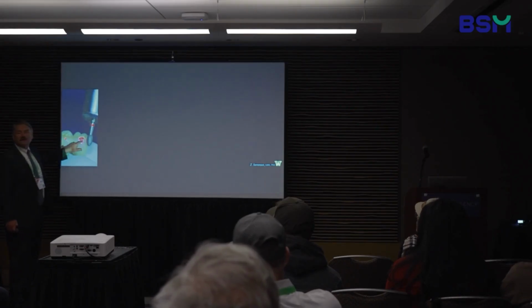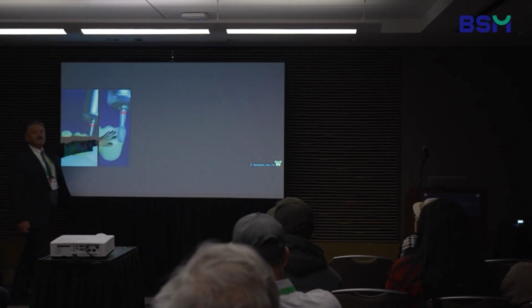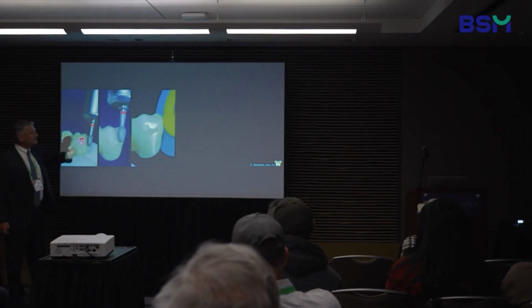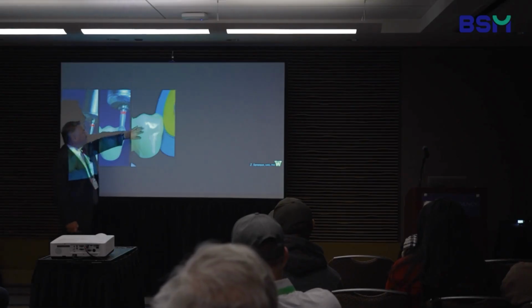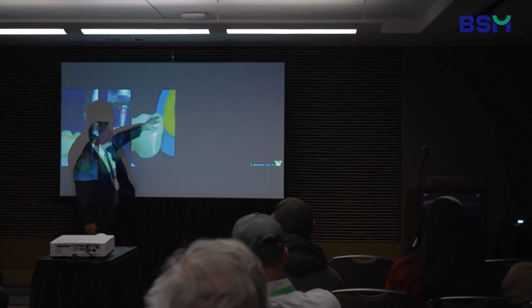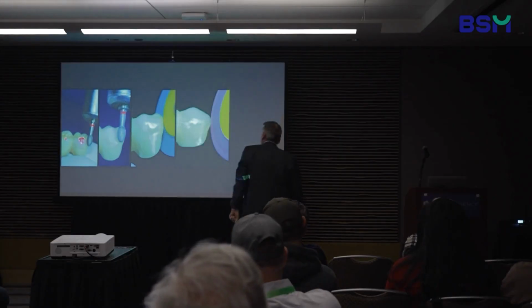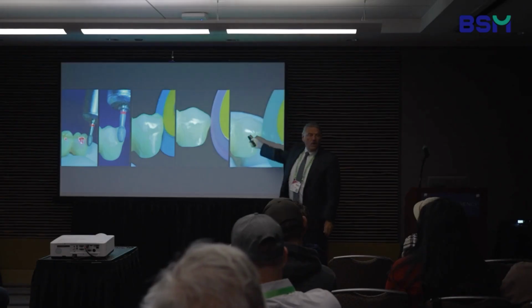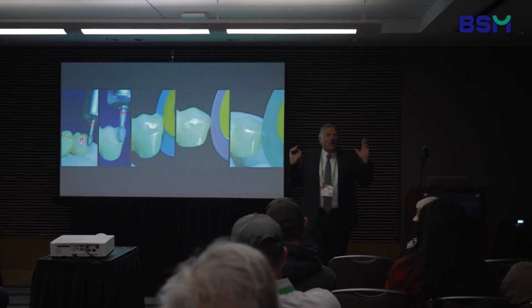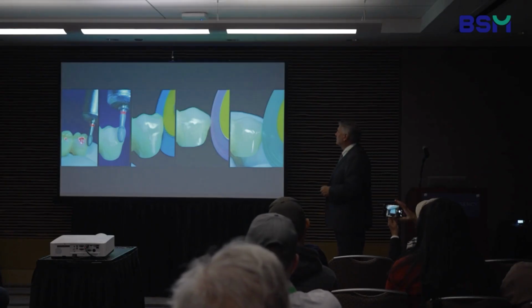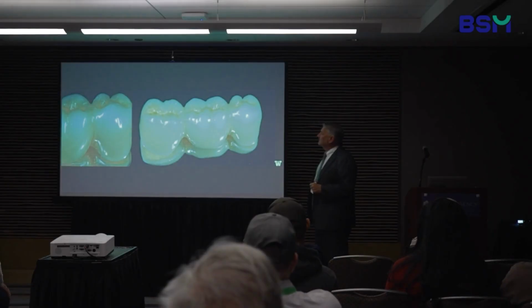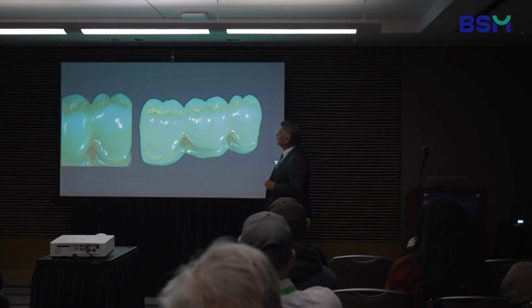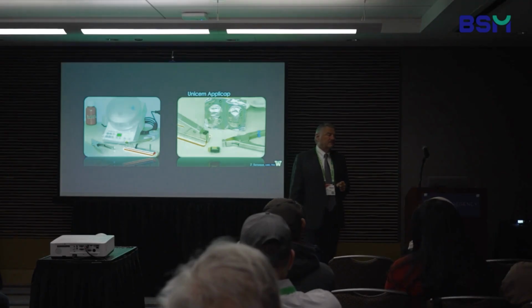And I can go in now, and here we're going to adjust the occlusion. So I'm using my red banded 30 micron finishing diamond to adjust that occlusion. And now I'm going to polish it up. So just to show you that, again, this is within the material, now I'm going to take the blue coarse Dialite polishing system. This is back with that original 3-step system. We go to the medium, and then we go to the fine, and what do you know, but we still have our colors in there. So again, now all the companies have these systems that are available, including what we're going to be talking about with their system today. But again, I just get this nice depth of translucency, a warm dentin appearance on the occlusals that looks natural. And then we're going to go ahead and cement this with the Unicem cement.